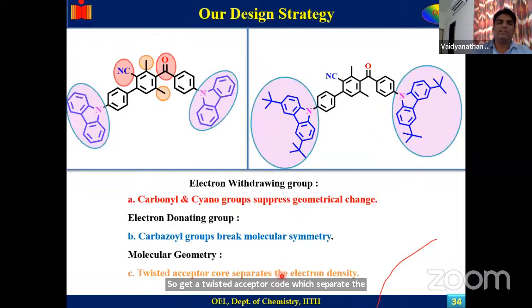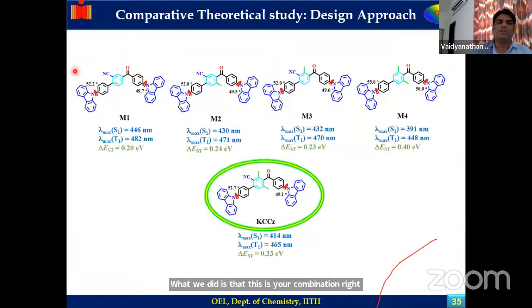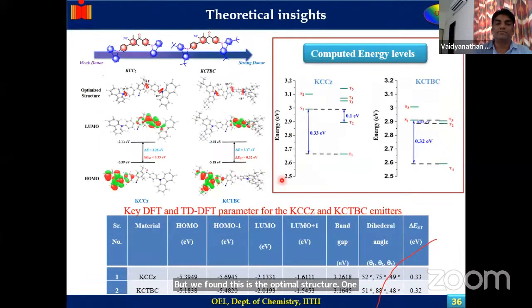What we did is this combination, right? So you have a 2-methyl, 1-cyanide. We tried only cyanide, only methyl, without cyanide, and 2-methyl with 1-cyanide. What we found is this is the optimal structure one can have to get better luminescence. We can also see here the S1-T1 gap is 0.1 and the S1-T2 gap is 0.03, which is very interesting.